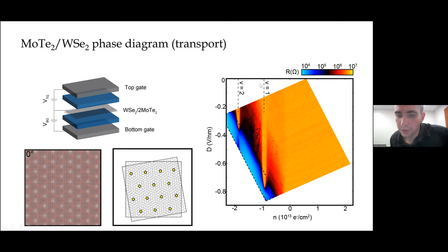At one hole per unit cell, you can see that there is an exchange gap that opens up over a pretty wide range of displacement fields. And indeed also at two holes per unit cell, you can see the superlattice gap, right? So this is coming from full filling or full depletion of the moiré band. This is indeed an exchange gap.